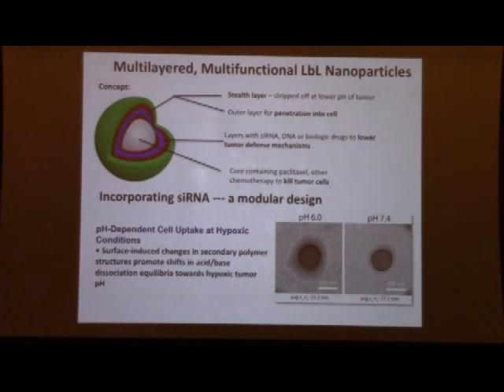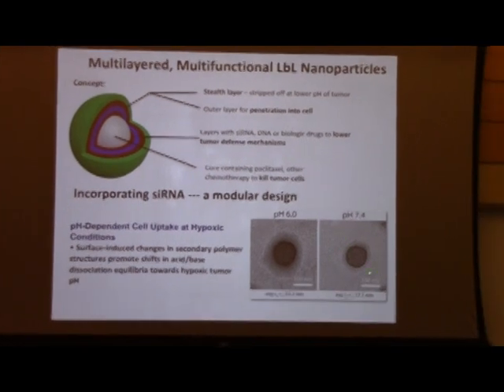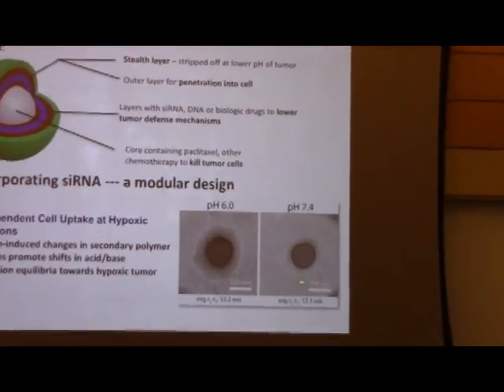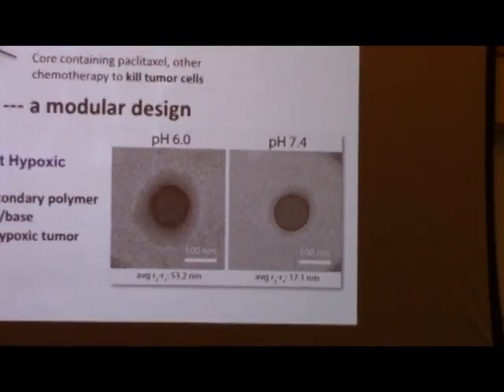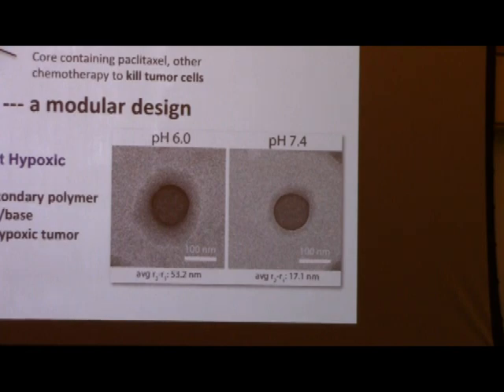It turns out that both of those two groups, for those who remember in light chemistry, can undergo a change in their relative charge with pH. So what happens is that at pH 7.4, the combination of these systems blended into a layer is net negatively charged. But as you begin to go to slightly lower pH, you're essentially erasing negative charge, because in chemistry talk, we are protonating the carboxylic acids. In regular talk, we are essentially eliminating that charge as we move down to lower pHs. And this becomes more of a neutral particle. So we lost some of that repulsion.